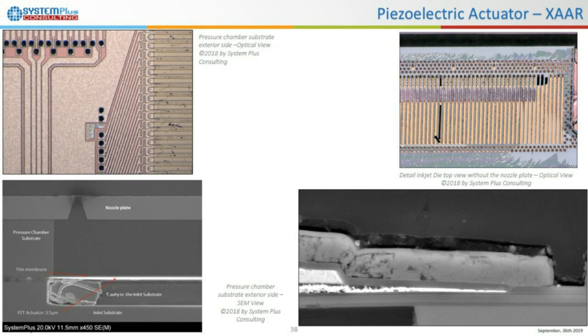For the Xaar inkjet die, it's easier because there are only 2 wafers, not 4 like for Epson, but the nozzle plate is not silicon; it is steel. You can see here the membrane with the piezo actuator, always in PZT, but here the thickness of the PZT is greater, about 2 micrometers, and the deposition process is more complex because there are not 5 layers but 8 or 10 layers of PZT to create the actuator.